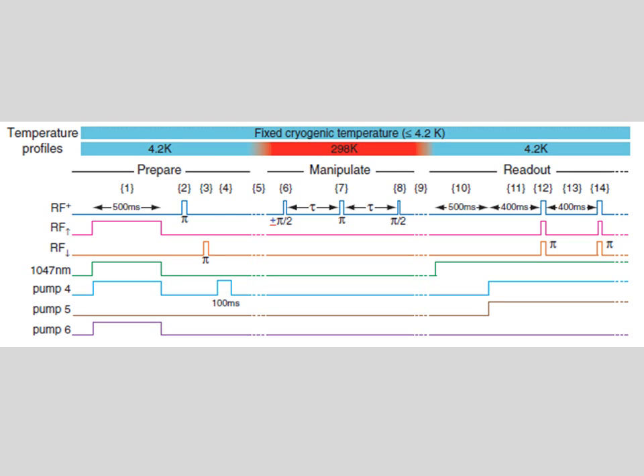Part of what Saeidi et al. did was to show that this system could be operated while the temperature is increased up to room temperature while the donor atom is ionized, as shown by the temperature bar at the top. The researchers accomplished this feat with an elaborate system of temperature controls, detailed in the supplementary materials. But it's important to note that the cycle takes about 12 minutes, so this is not a rapid process. It is only possible because of the long coherence times of this system, and shows why enriched silicon is absolutely essential.